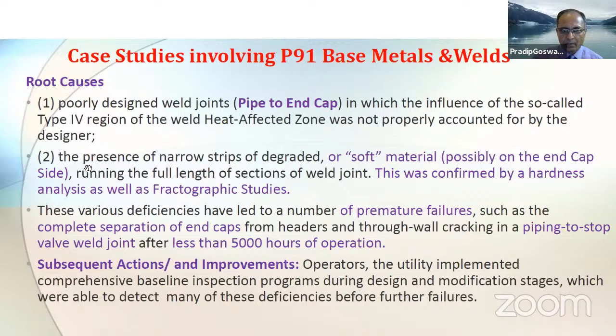The presence of a narrow strip of degraded soft material, possibly on the end cap side, was confirmed by the hardness analysis as well as the fractography studies. The various deficiencies led to a number of premature failures, such as the complete separation of end caps from the headers and through-wall cracking of pipe to stop valves after less than 5,000 hours of operation. So 5,000 hours are nothing in the context of any utility.